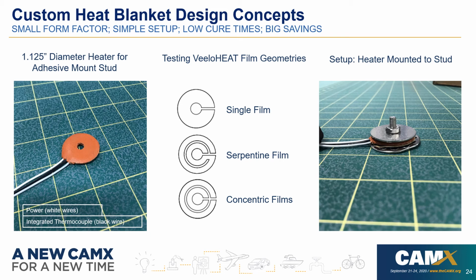The reason why we did that is we anticipated with the single film design that there would be a temperature gradient, as the path length on the inner diameter of the heater is much shorter than that of the outer diameter. Here in the image on the right is a mock-up of the heater blanket mounted to the stud.